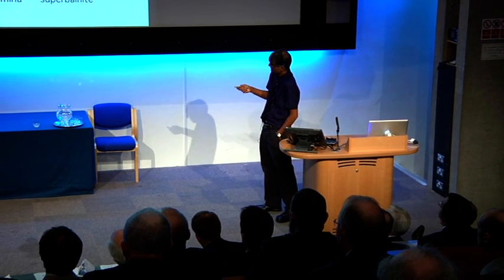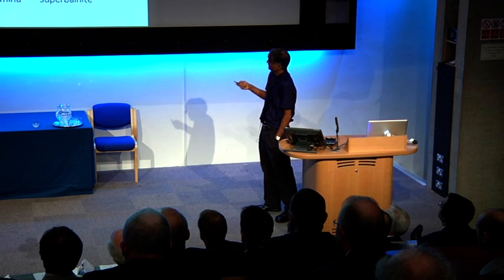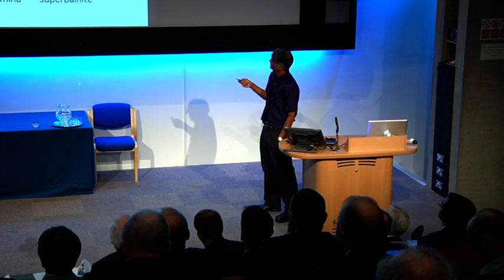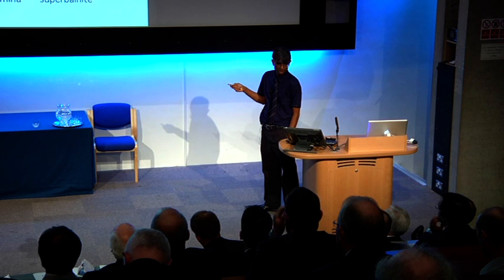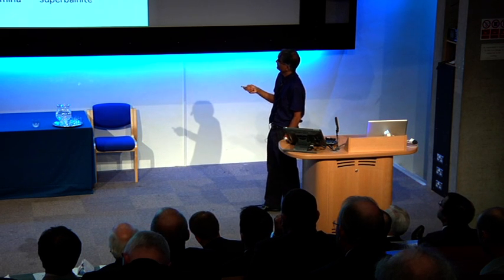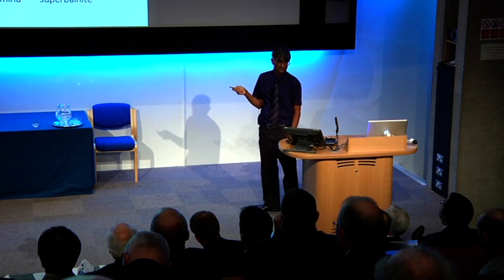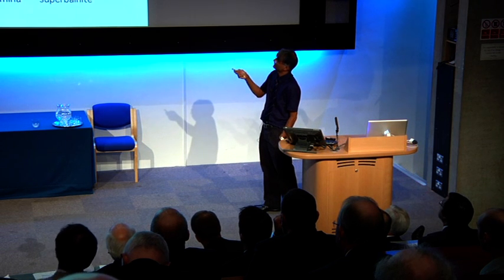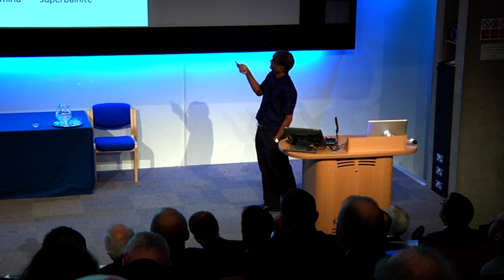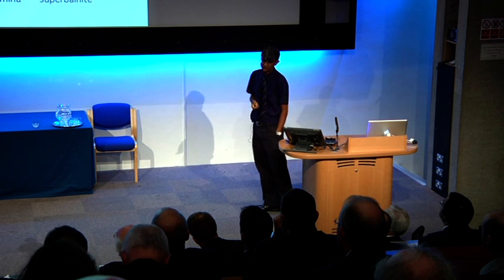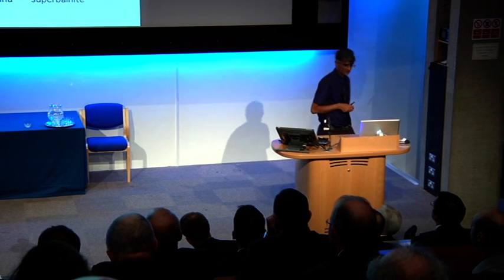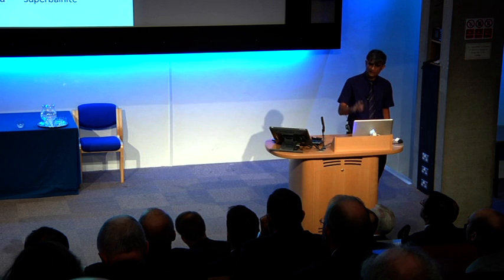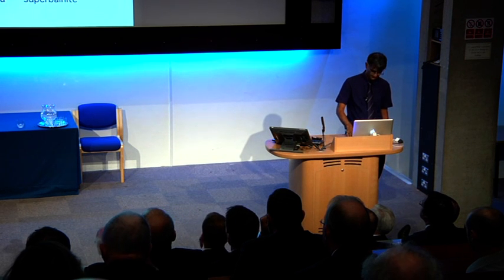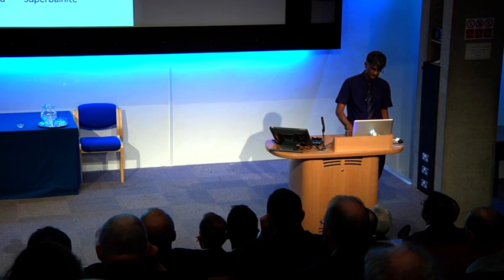So this is conventional armor, this is titanium, alumina, and this is now the super bainite. So alumina can't take many shots for obvious reasons, okay? And this is corrected for density, because this is a ballistic mass efficiency. It's the mass of ordinary armor to defeat a given threat over the mass of a test material to defeat the same threat. So it outperforms normal armor, even if it's made out of titanium.